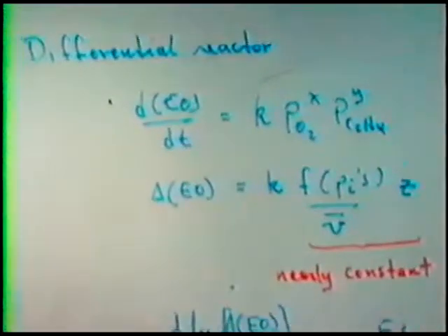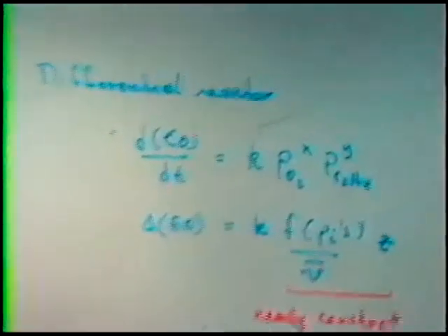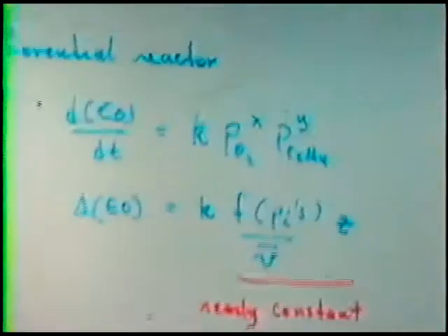Now, it's possible, using that 1-to-1 pulse mixture, and a constant pulse size, to vary the temperature in the reactor and to observe the amount of ethylene oxide formed. And since we're dealing with a reactor in which we only have 1% conversion, no matter how you view the details of the reactor itself, because the partial pressures in the reactor stay effectively constant due to the low conversion, one can extract from the amount of product formed as a function of the catalyst temperature a characteristic activation energy.